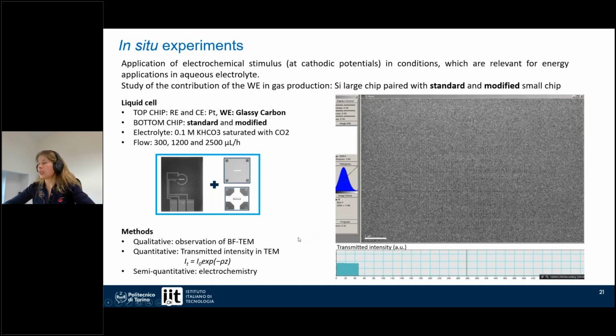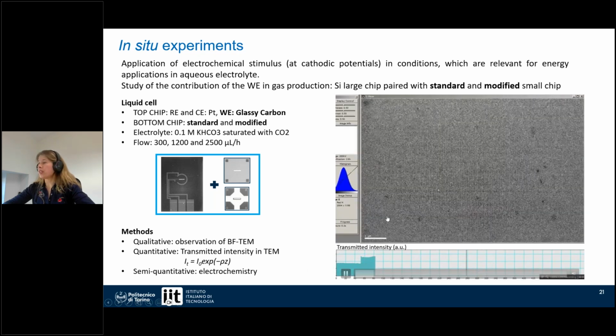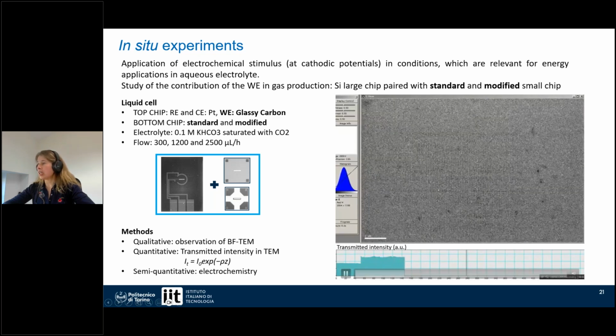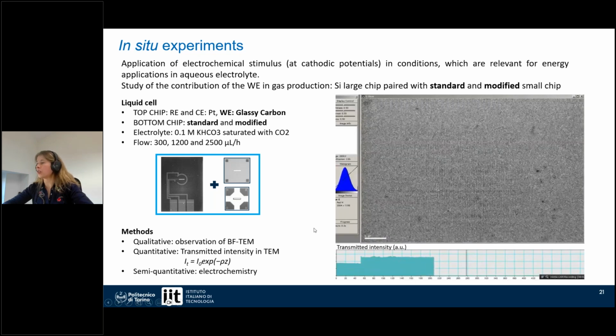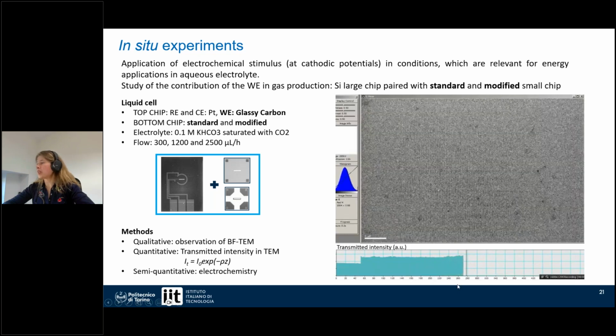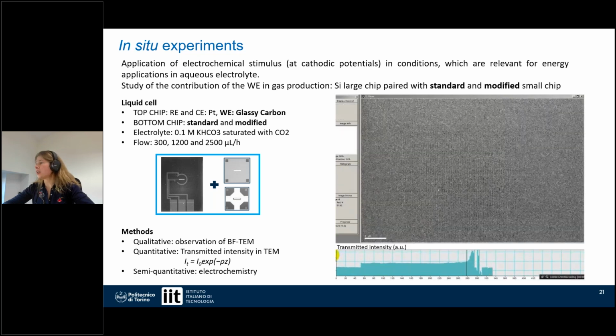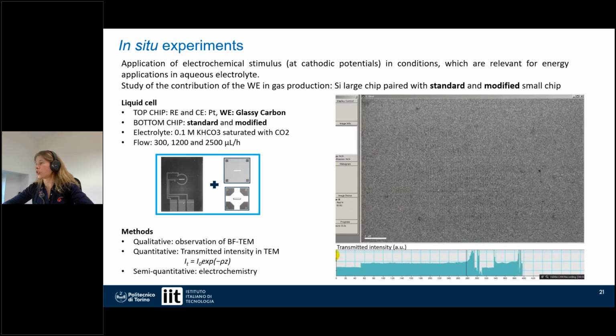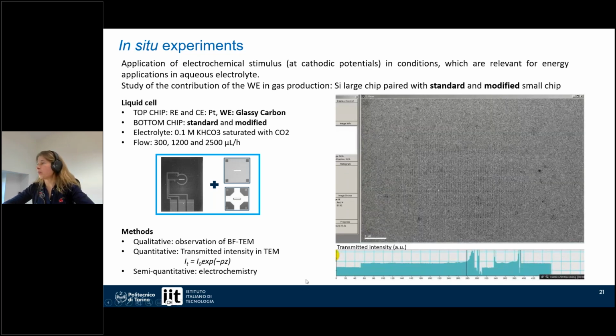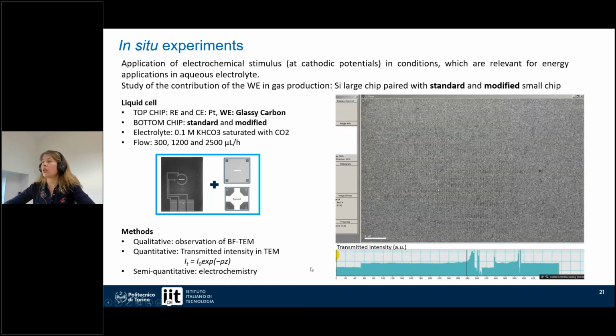So here I show you the transmitted intensity acquired during running the chronoamperometry in one of the cells. We start with the full cell, and the transmitted intensity in the TEM is low. Now I will show you what is happening. Once the bubble is produced within the cell, the intensity is increasing, and you can observe that there are actually some particles on top of the working electrode. And then you will see some dynamics and passing of the bubble. There is some gas within the cell, and the bubbles and the electrolyte are pushing themselves away. So this is just to show what we are observing in TEM when we are investigating what is happening on the working electrode.